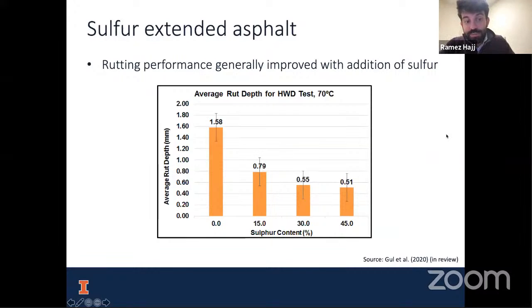Rutting, actually, what we found generally improved with the addition of sulfur. So the most permanent deformation was observed with 0% sulfur. Then as we increased to 15, 30, and 45, we saw a continuous decrease, although these are all statistically very similar. We did see quite a good impact of the addition of sulfur. So we felt good about using this from a rutting perspective. However, what about a cracking perspective?